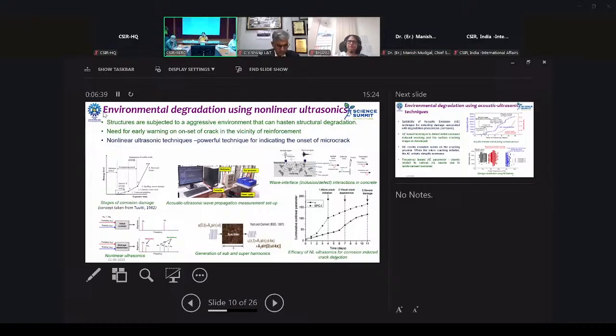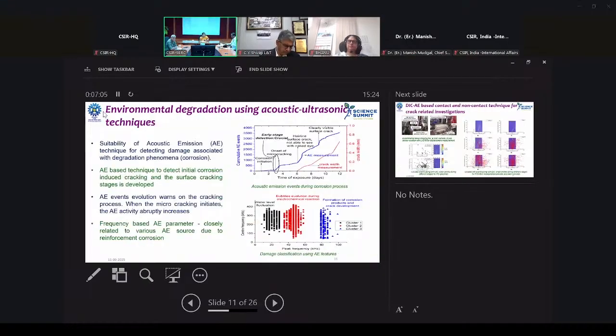And when corrosion starts, it makes the structure very weak, cracks will come out, and that will create a sudden failure. Now the challenge was when the micro crack starts in the vicinity of the reinforcement due to the pressure created by the corrosion, whether we would be able to capture that initial stage. And it is so interesting to see that by using the nonlinear ultrasonic or the acoustic emission,